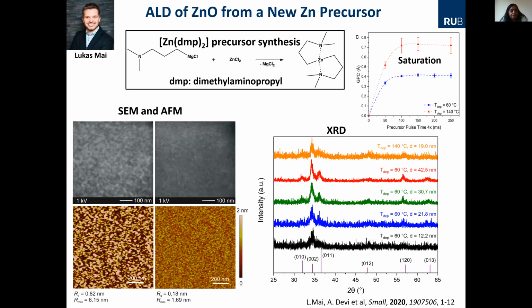And with the same ligand, once more, Lucas, during his PhD, tried it for zinc. Zinc oxide is also a very cheap material and very interesting for different applications. Here also we used a similar ligand and made a zinc precursor. What we saw is that the films are smooth, even at very low thickness. At deposition temperatures of, for example, 60 degrees or 140 degrees centigrade, they're crystalline, nanocrystalline I would say, not highly crystalline, which is normal because ALD is a low temperature process, and the ALD characteristics were confirmed.